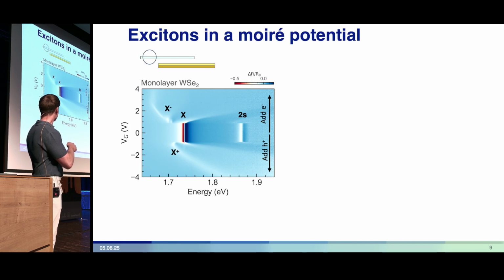At a gate voltage of 0, we have a charge neutral state where we have this state, X, the neutral A exciton in WSe2, and an excited state, a Rydberg exciton. As we add electrons or holes to the system, we generate negatively charged trions, 3-body states, or positive trions, which tell us that the sample is charged.